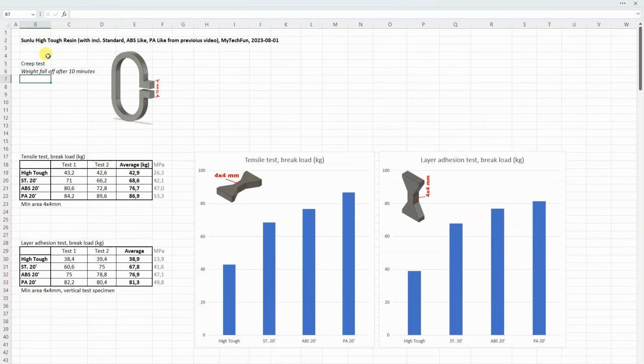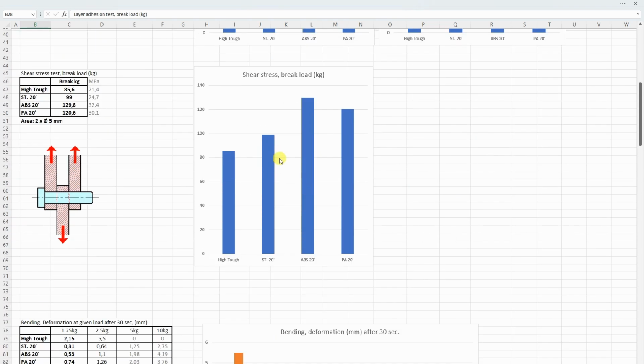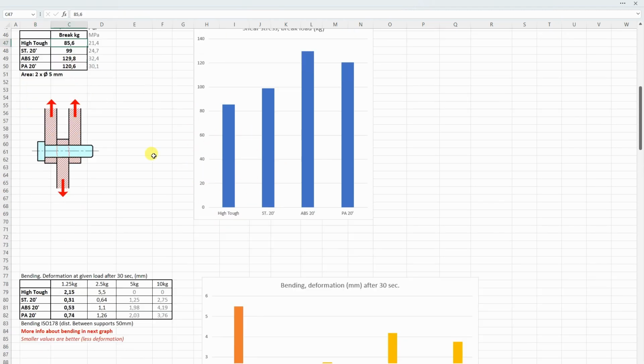Let's summarize the results in this Excel table, and I will include here the results from the previous video. These are 20-minute cured versions because I had 2 and 20 minutes for the comparison. The creep test, well, you saw the weight fall off after 10 minutes, so that is not included in this table. The tensile test and the layer adhesion test, you can see on this graph that the high tough resin was the weakest in this test, but interesting that it is equal, independent from the orientation of the printing. The shear stress, it was again weakest, but the difference is much smaller.